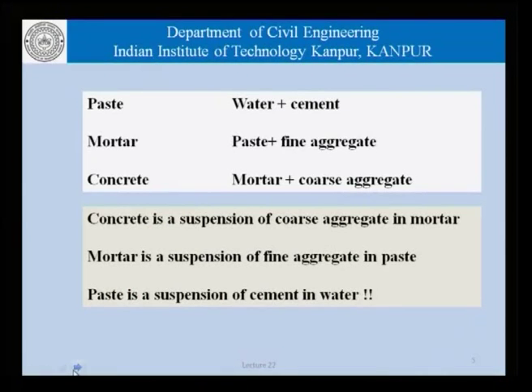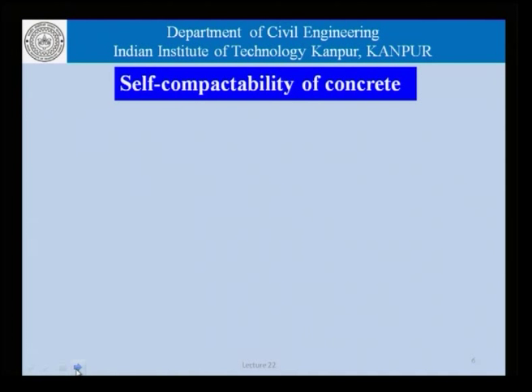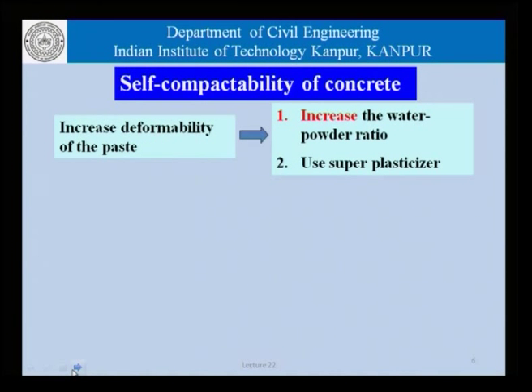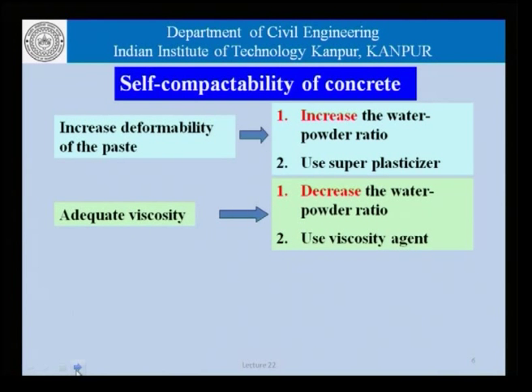Continuing with that discussion and reiterating that paste is water and cement, mortar is paste and fine aggregate, concrete being mortar and coarse aggregate, and the suspensions as we have discussed. We now talk about self-compactibility of concrete, where we said that on the one hand, we need increased deformability of the paste, which calls for an increase in the water to powder ratio and the use of superplasticizers. And on the other hand, we require adequate viscosity, and for that we need to reduce the water powder ratio and we use viscosity agents.